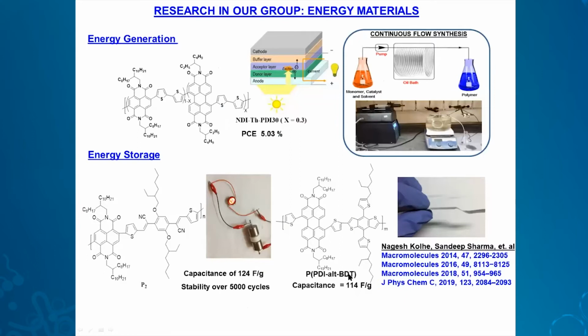Summarized in this slide are a couple of approaches that we adopted with this type of materials, especially the N2200 polymers. As I mentioned earlier, these two units make up the N2200. It can lead to aggregation, leading to poor device performance. To overcome this, we designed a copolymer by incorporating its higher analog, the perylene diimide, randomly along the backbone in various mole ratios. After studying various mole ratios, we found that about 30 mole percent of this leads to a very optimum result. And when this is used as an acceptor layer along with PTB7-Th as a donor polymer in an all-polymer solar cell device, we obtain 5% power conversion efficiency.